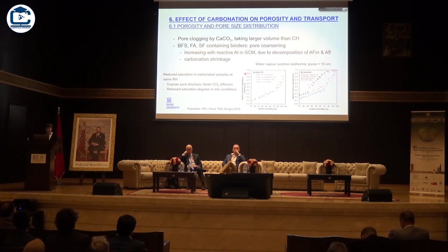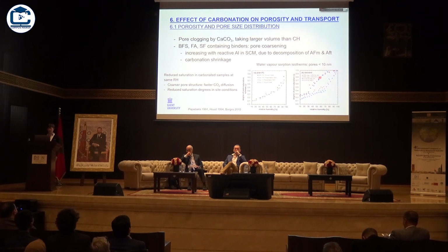Actually here it is seen that if you look at, for instance, the effect of water saturation in plain Portland cement and blended cement samples, you have a different effect on the pore structure. Here, for the plain cement, these are absorption isotherms, not much is changing with carbonation, whereas if you have SCMs present, there is a difference between the carbonated and the non-carbonated samples, which means there is an implication for the changes in pore structure, and you have more coarser pores also in the considered region here.